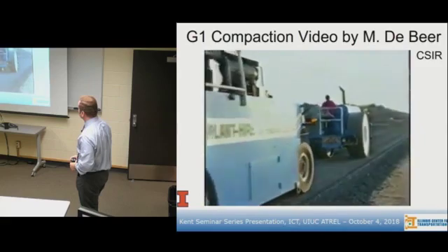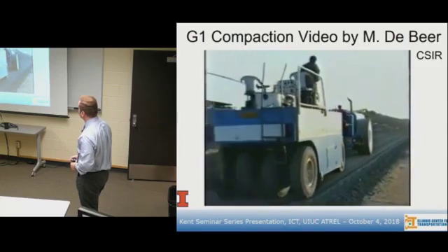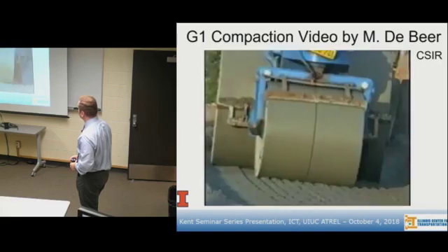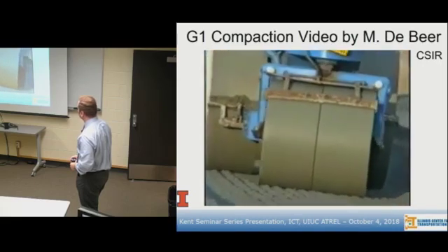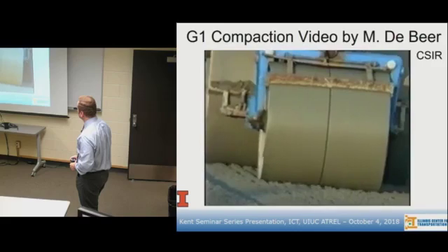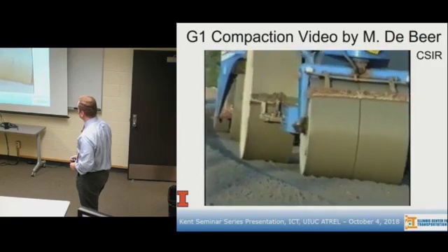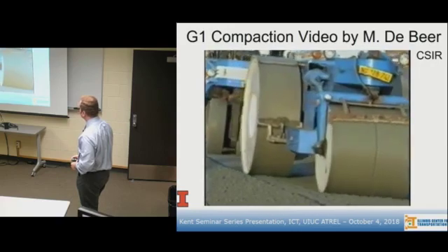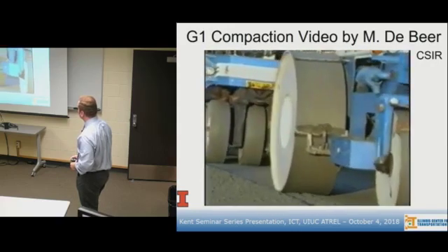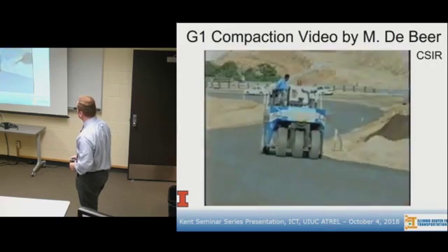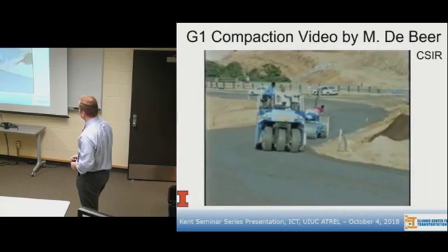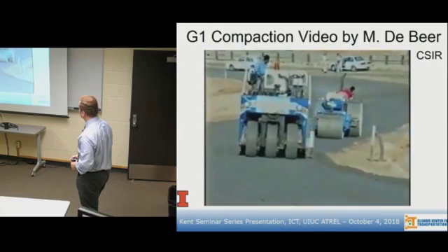Other non-vibratory rollers may assist, especially the heavy pneumatic tired roller. Note that the compaction rolling should start at the outer edges or lowest cross-section side of the pavement and progress towards the center or higher cross-section side of the pavement. Successive passes with the driving wheels leading, to prevent bow waving of the material and corrugation formation, should be applied in the same lane in opposite directions.